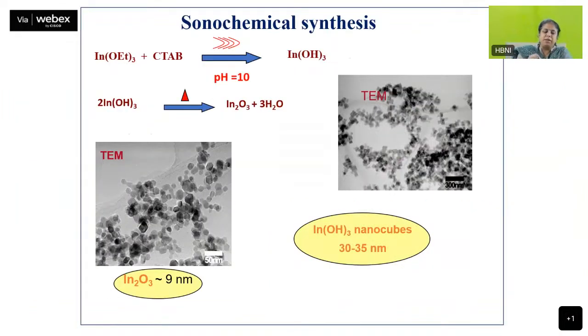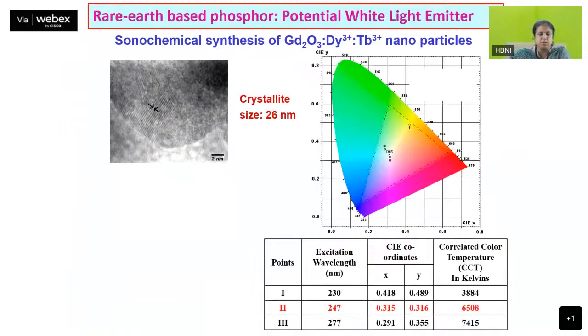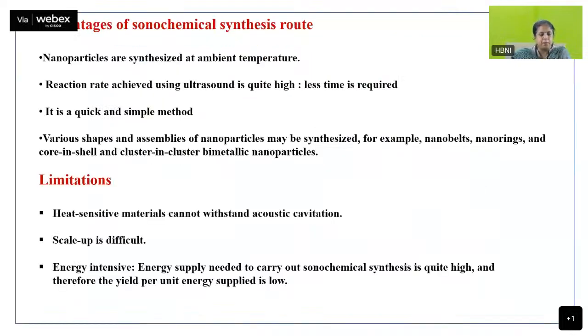One example of a sonochemical reaction: we wanted to synthesize indium oxide for optical application. We started with indium ethoxide and used this as a hydrolyzing agent as well as a capping agent. Put it under the sonochemical condition, we got indium hydroxide. And this is the TEM of indium hydroxide. Nice cubes were obtained. Heated them, we got 9 nanometer size indium oxide particles. Very, very simple synthesis. Of course, you can extrapolate it to complex oxides. And then it was used as a white light emitting material.